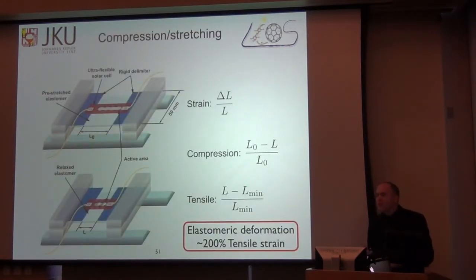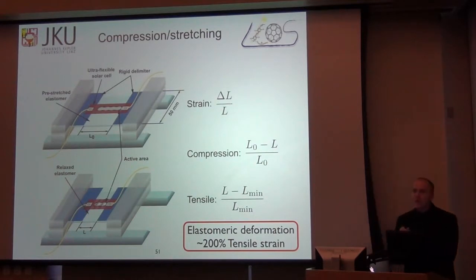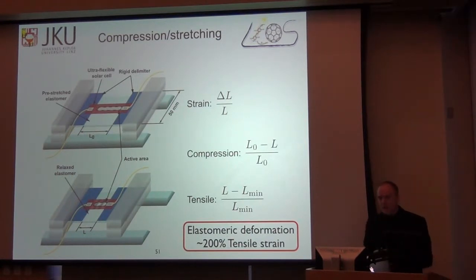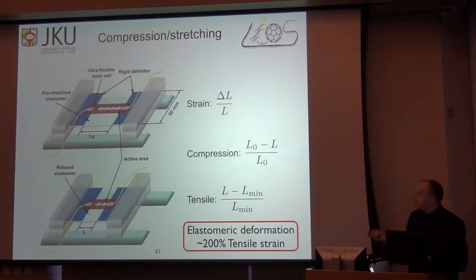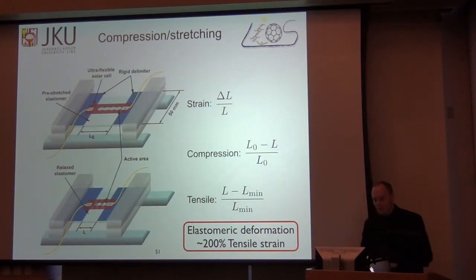It's also not particularly quantitative. So instead, we tried to subject the solar cells to the most extreme form of deformation we could possibly think of. What we did was we took an elastomer, it's basically a rubber band, we stretch it, we glued the solar cell onto it, and we relax the elastomer. And in doing so, it forms a random network of wrinkles and folds that are really brutal looking. And then we can re-stretch and recompress the solar cell as we please. We define an effective stretching strain as change in length over length, compression being normalized to the flat state, and tensile strain being normalized to the minimum length over which you compress it.